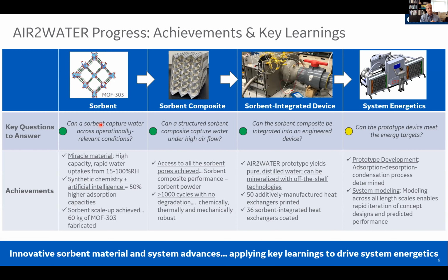Yes, it absolutely can. It does this anywhere from 15% relative humidity, all the way up to 100% relative humidity. As I said earlier, the coupling of synthetic chemistry plus artificial intelligence is now enabling 50% higher adsorption capacities.